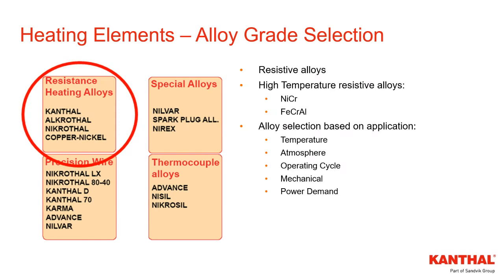So you have to consider quite a few things, such as the temperature of the furnace, and that's how it's going to relate to the oxidation and strength of the heating element, the atmosphere of the furnace or the application, and that affects the operation, the presence of the element, or if there is any presence of chemicals or gases you might have to consider. Then the operating cycle of the furnace. So it's related to how the furnace is run. So whether it's just an on-off, either the furnace is running or it's not. You might have intermittent use where you might be cycling it occasionally. And then you have continuous use where it's always on.